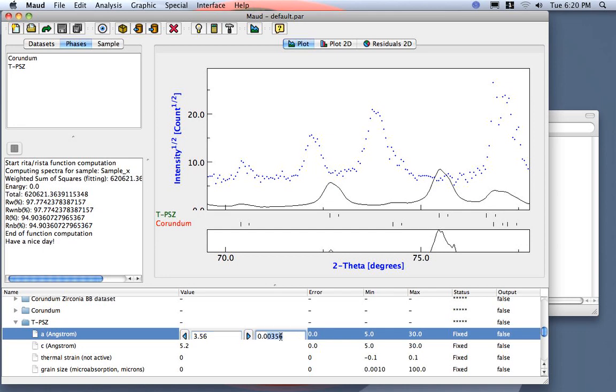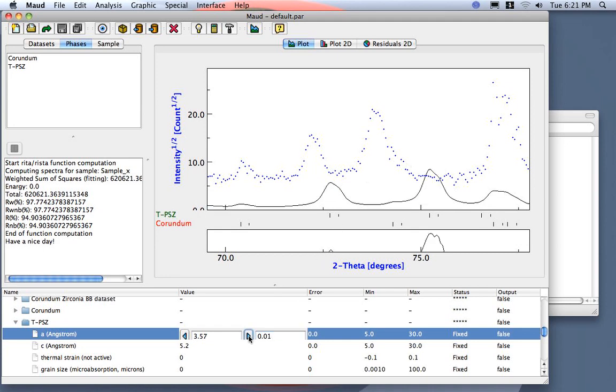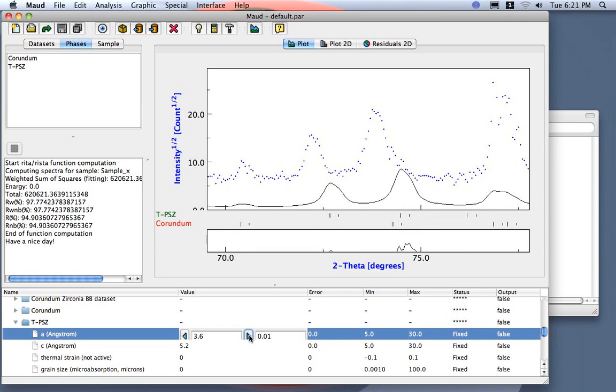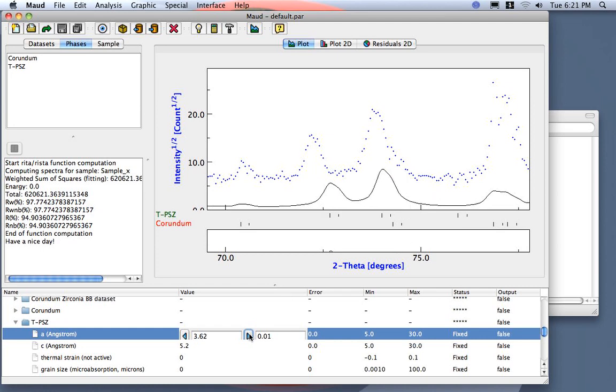We select a bigger step than this one, for example we change by 0.01 and we need actually to increase. As we want to move this, the 2-2-0, we need to move this one over here, so let's increase. You see we are just moving only this peak here, not this one. So it's more easy just to adjust one by one the same parameter. So actually we are inside here.